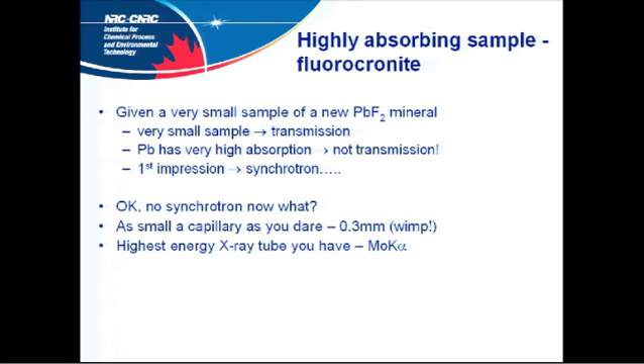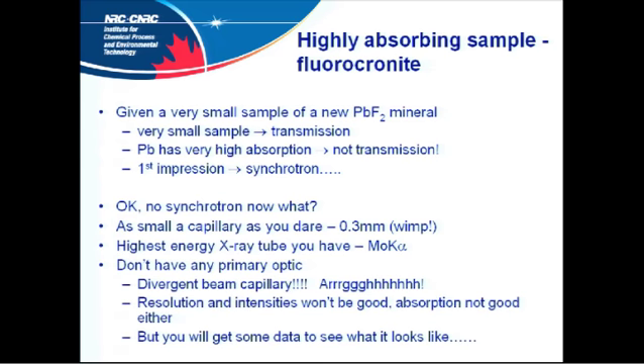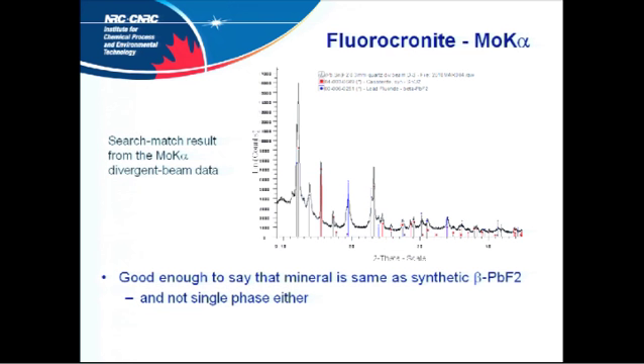Highest energy X-ray tube I had, in this instance, was moly. I've actually got a silver tube now, but at that time I didn't. Unfortunately, for my moly, I don't have any primary optic, so I had to try this on an old-fashioned divergent beam capillary, which is not my ideal experiment. The resolution and intensities aren't going to be wonderful, and if you work out the theoretical absorption even with moly on a 0.3 capillary, the absorption is still pretty high. But you'll get a little bit of data to see what it looks like.